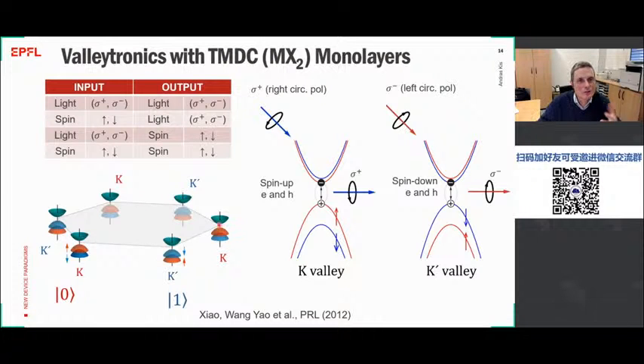So in the beginning, we thought that we could realize some kind of Valleytronics devices by looking at all these different possible combinations of inputs and outputs. So we can excite valleys using circularly polarized light or using spin injection, and then we can also read them out using light detection or spin detection. And we were trying to play along a lot with different types of devices using ferromagnetic electrodes, etc. But then we realized that the best and maybe the most efficient way to realize this type of devices is to use actually directly excitons and manipulate charges at the level of excitons and not at the level of single charges.